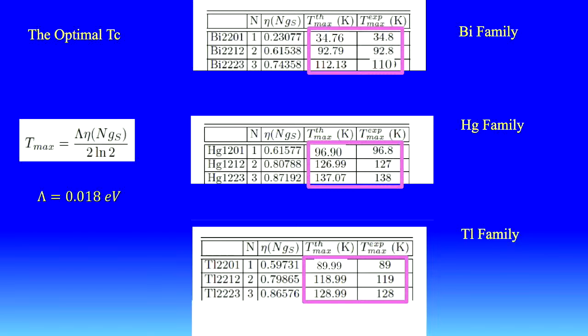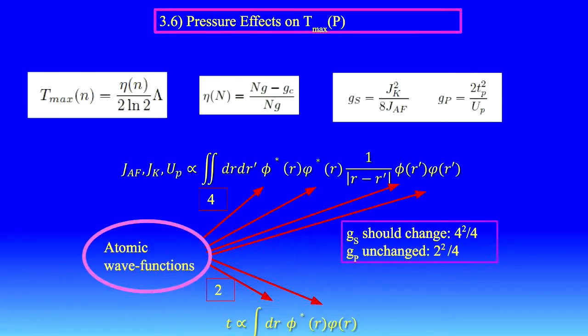So this explains the increase of the temperature according to the number of planes of the family. Now, pressure effects. So I have this expression for maximum temperature. This eta is that function, and if I want to see the effect on TC, I display GS here. And if I want to see the effect on the pseudo gap, I plug this in there.